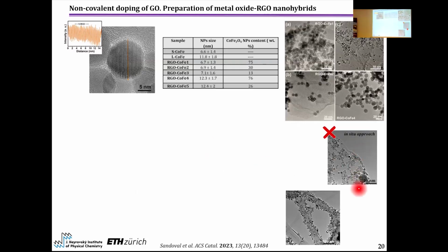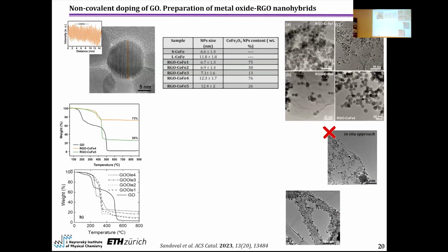This is, for example, the particles prepared using the same protocol, but using the in situ approach. I mean, putting the precursors inside the reactor, but not preparing the particles before. So we can see that in this case, for example, we have very big particles, and we cannot tune and control the size of the particle. And also the protocol is very versatile because it can be applied to the modification of other nanostructures.